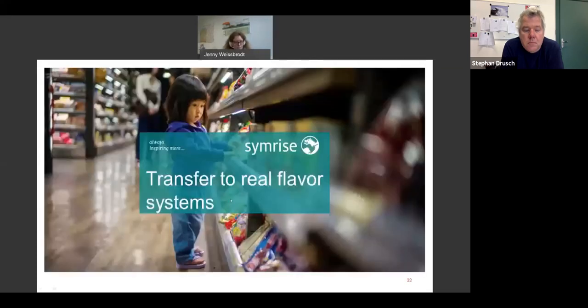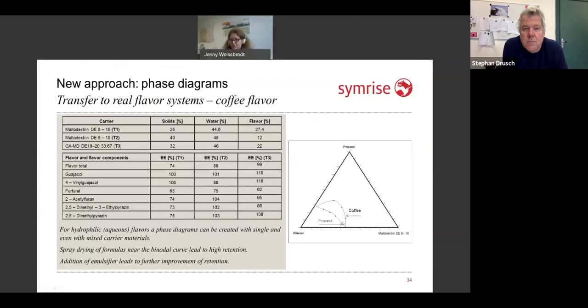Now the question was, could we transfer this idea to a real flavor system? We selected a coffee flavor, which is mainly based on water-soluble components, and tried to establish a binodal curve for this flavor in a carrier system too, and it was possible. One of the main components of this coffee flavor is propanol. Here's a propanol curve. The coffee flavor curve looks completely different, but it was possible to establish this binodal curve. And now we are testing out points on this binodal curve, because the idea was, if we know that increased solid will improve the encapsulation efficiency, does it even work when I just walk around the binodal curve?